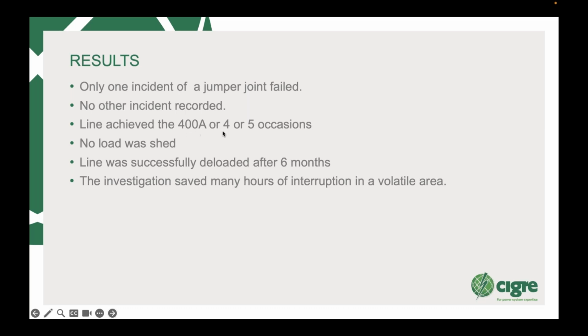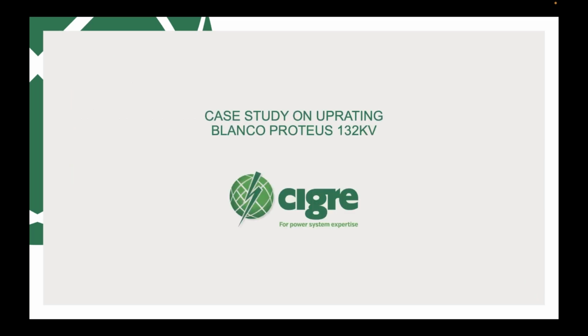The line achieved 400 amps on four or five occasions. So this is a very small amount of time. There was no load shed. And then the line was successfully deloaded after 6 months because we had strengthening of the system. So the investigation that we managed to do here without really doing much on the line at all, besides inspecting it and making sure the clearances were okay, was that we saved many hours of interruption in a very volatile area, supplying areas in townships in the Western Cape.